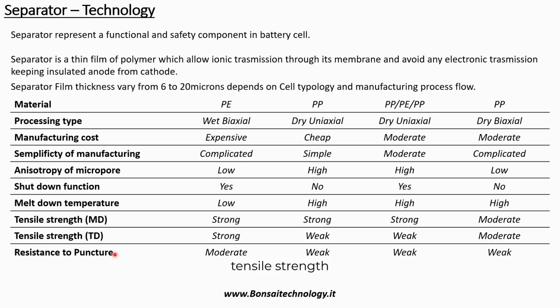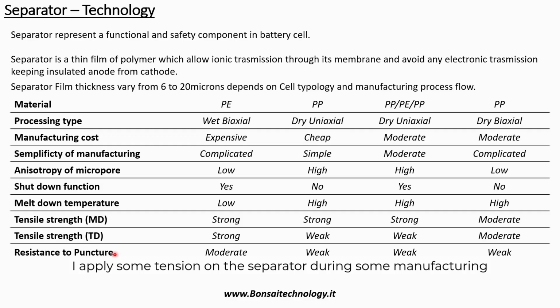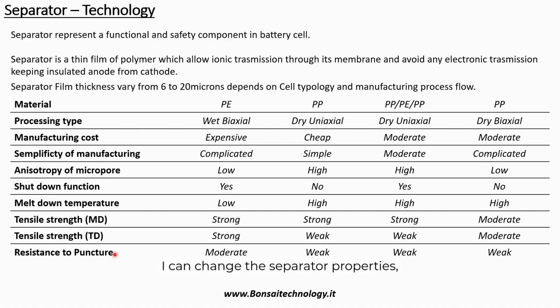Else, if my tensile strength in the main direction is not sufficient, and I apply some tension on the separator during some manufacturing process, I can change the separator's physical properties. I mean, I can change the thickness, I can change the porosity in terms of size, in terms of distribution. This for sure will have an impact on the safety, because if I have a thinner separator, this could be a problem. But I can even have a problem in terms of performance, because I don't have any control in terms of porosity. So even the lithium ion flow changes from the nominal condition.